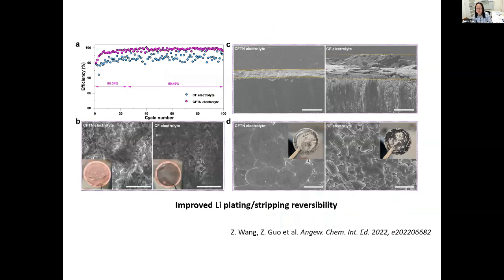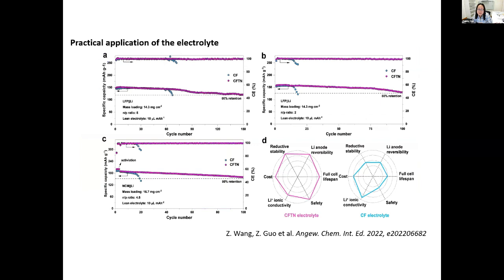Then we evaluated the electrochemical performance. We found in the lithium-copper asymmetric cell, the average coulombic efficiency is about 99.5%, suggesting the lithium plating and stripping reversibility in this electrolyte is quite good. And also, we found that the lithium deposition in this electrolyte is in quite large pieces and quite dense. On the other hand, for the baseline electrolyte, you can see the deposition is quite porous and not as dense as the deposition in our non-flammable electrolyte, suggesting the plating and stripping reversibility is not as good as ours.